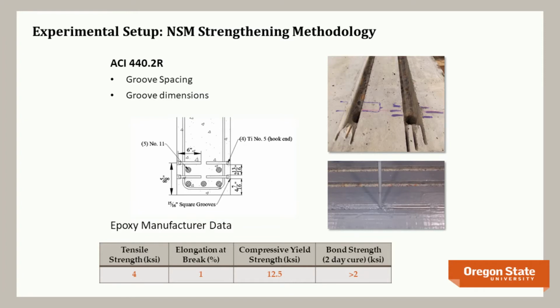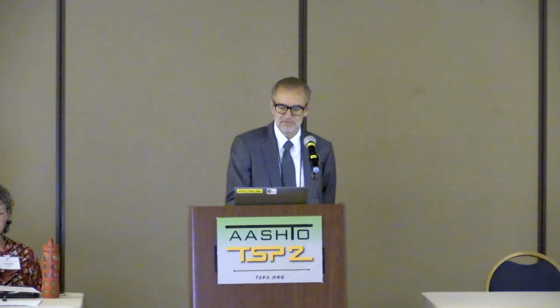So here's a picture of the construction. We've cut the grooves here, essentially 3 saw cuts, passes, and then with a chisel you kind of just chip them out. And then at the end of each one of those grooves we hammer drill a hole that's going to anchor in our hook. We're using ACI 440, which is the FRP specification in terms of groove spacing and the groove dimensions.